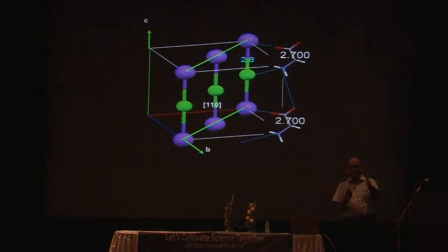As I said again, the rule, aage gele bage khai, pore gele sona khai. So therefore glycine is doing the job. Glycine just binds to the 1,1,0 surface when the crystal grows, and this particular surface grows slower than the other faces. As a result, at the end of the day, what you get is a rhombic dodecahedron.